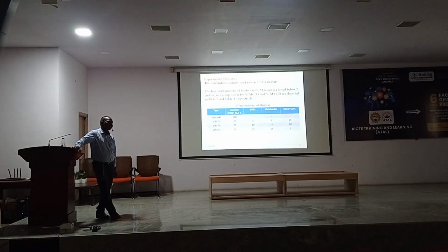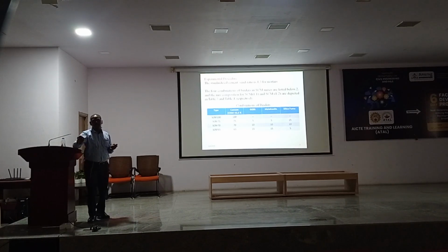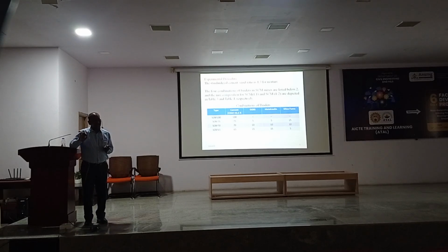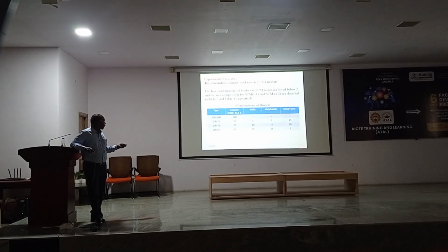The cement to sand ratio is 1:3, as per our code also, we are following 1:3 only. And there are two mixes, 1:1 and 1:2. I am taking 4 combinations like this. What I told, 35% of the material is supplementary cementitious material. SCM 65 means 65 cement, remaining all 35 SCM. SCM 100 means 100% cement, there is no extra material. SCM 75 means 75% cement, 5% GGBS, 5% metakaolin, 15% silica fume. That means more silica fume, what is the advantage? And less silica fume, what is the advantage? And all three equal, what is the advantage?